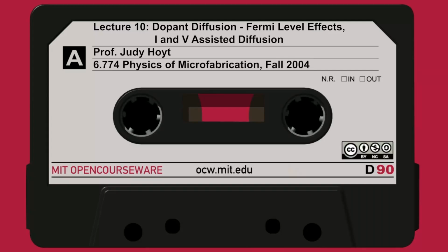We're assuming the base was grown by epitaxial crystal growth. We'll talk later in the course about what that is. But it has a very abrupt constant doping profile like this. It's about 1,000 angstroms. And then you deposit a layer of N plus polysilicon on top, and that gives you this high arsenic concentration. And what you're interested in is annealing this to drive in the arsenic a little ways into the epi, into the base, for 1,000 degrees for 30 minutes. And you want to see what the profile looks like.